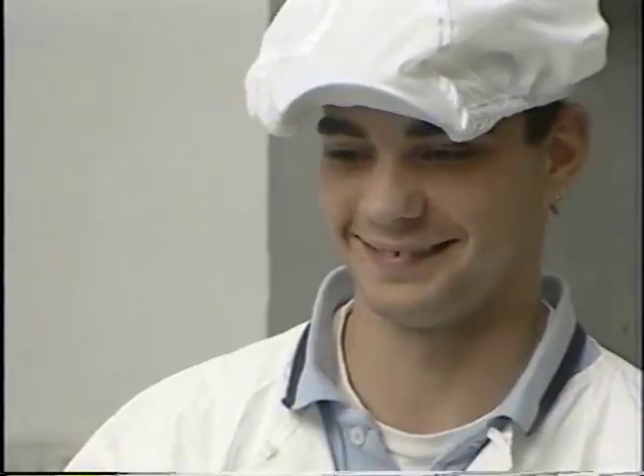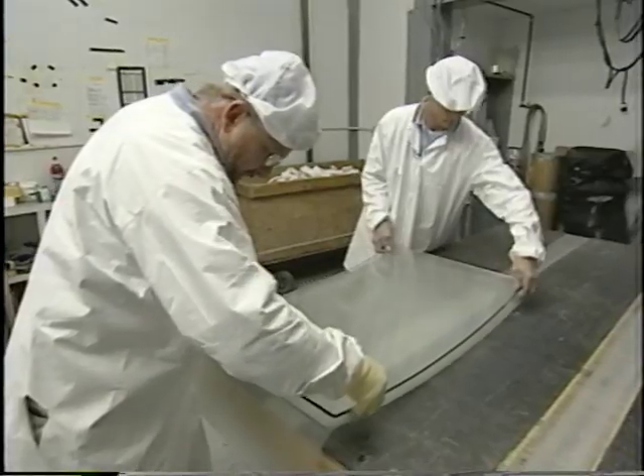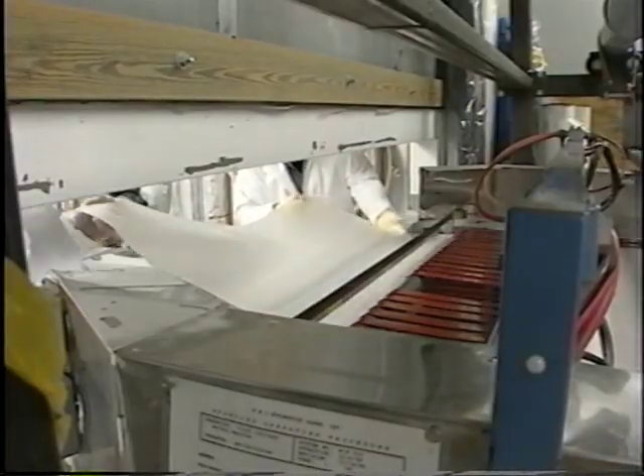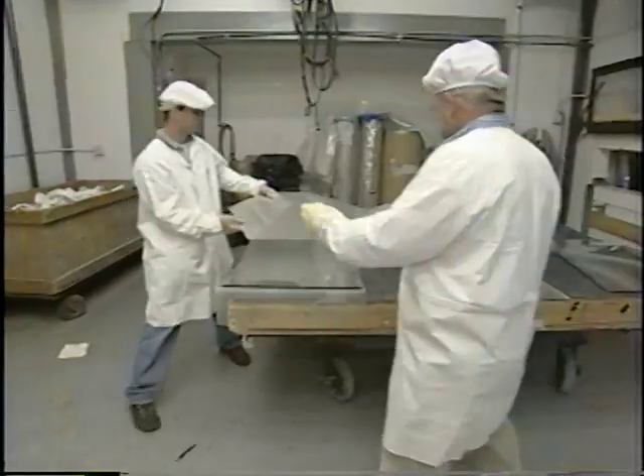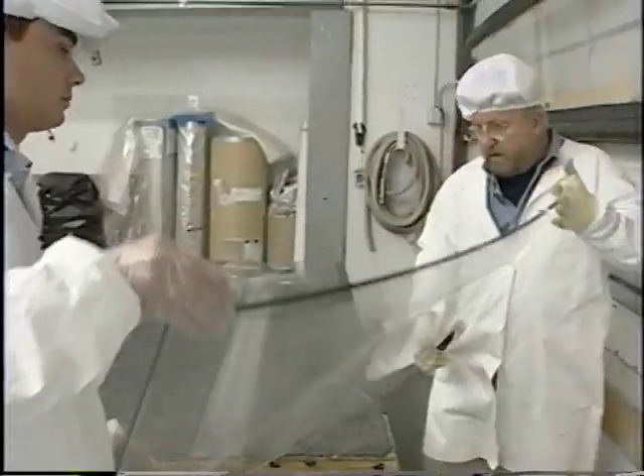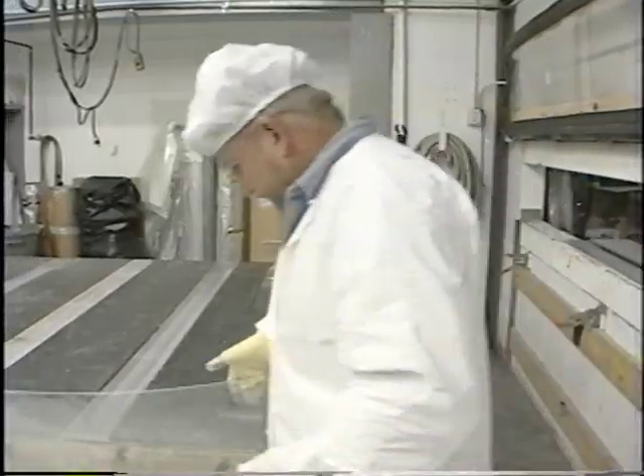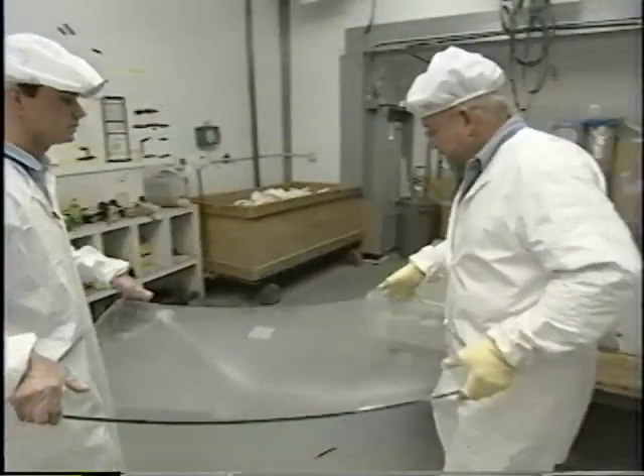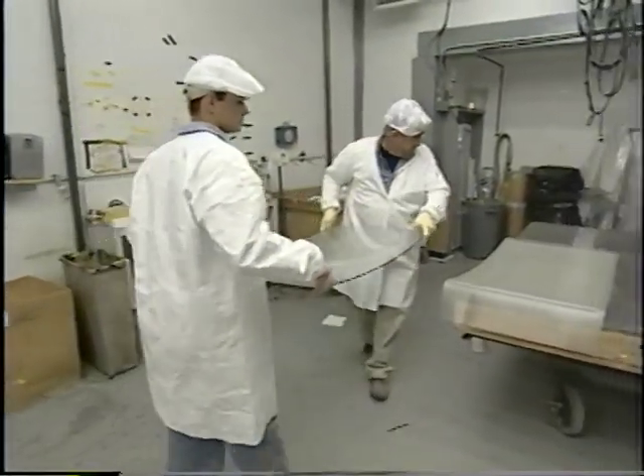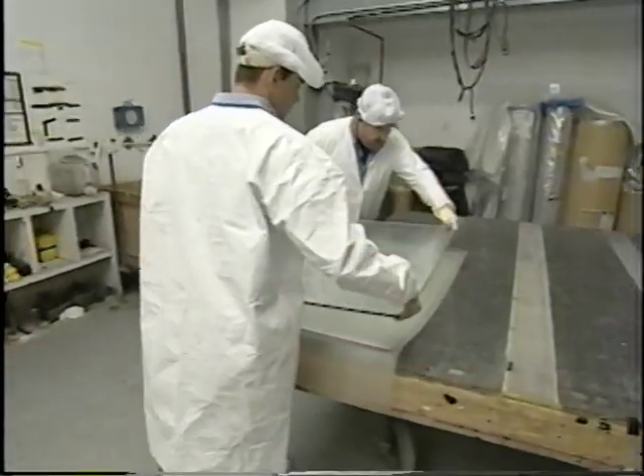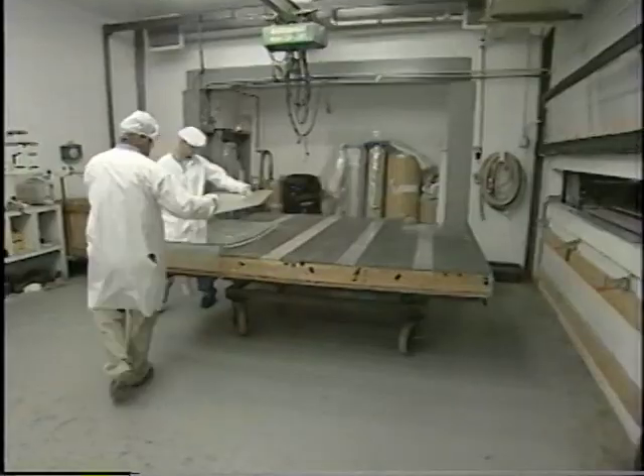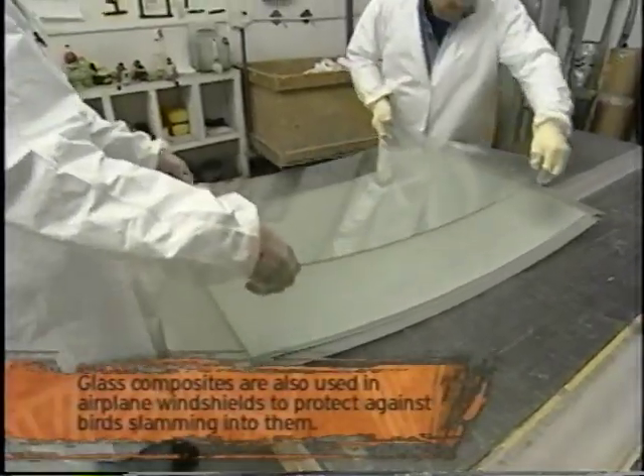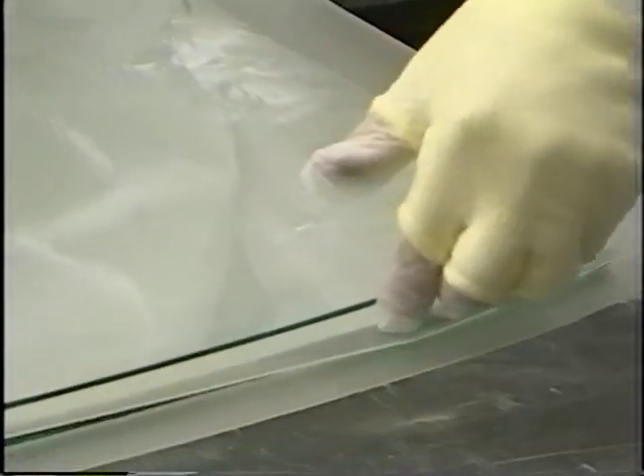Wow, that's thicker than I imagined it would be. The PVB is cloudy because it has a rough surface for gripping the glass. Once it melts and bonds the glass together, it will become transparent. I got the mark right here. It takes 3 sheets of PVB layered between 4 sheets of glass to stop a 9mm bullet at 15 feet. This is quite a sandwich we got going here.